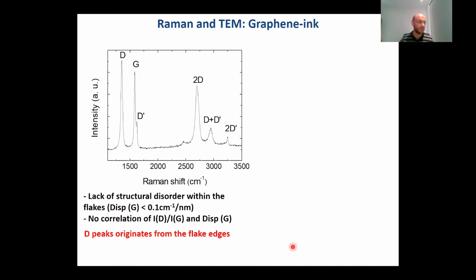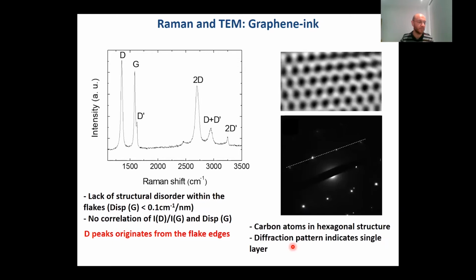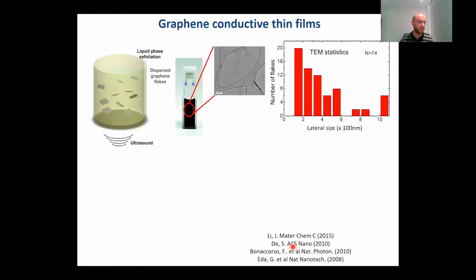Indeed, there are no in-plane defects in, for example, graphene flakes, as you can see from Raman, and high resolution TEM confirms the same. So we have a very reliable and robust exfoliation technique to make these inks. And this can be done in a way that creates dispersions with a high concentration. So you can get concentrations up to tens of grams per liter, for example, with graphene.